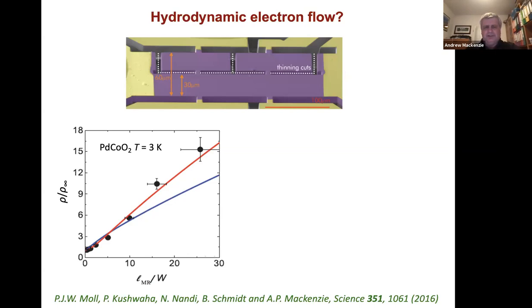So one of the first things we did when we realized that we could get this sculpting to work, this time in collaboration with Philip Moll, who was then still at ETH Zurich, is we got some crystals together. Philip made a conducting channel in the crystal and then did a very simple experiment where the channel we were looking at began as being 60 microns wide. Then he narrowed it in factors of 2, 30, 15, and so on, down to just below 1 micron. And we measured the resistance of electron flow through that channel at every narrowing stage. I don't want to talk to you about this in too much detail because it's an old paper now and you can read it at your leisure.